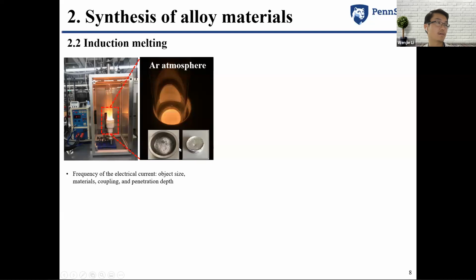we can get this molten metal homogeneous under the argon atmosphere. This is a picture of how the ingot looks. But normally, in order to achieve a homogeneous ingot, we repeat this heating and cooling a couple of times. Based on the object size, how good the conductivity of the material is, how the induction heating couples with the material, and also the penetration depth, we need to determine how high a frequency of electrical current we want to use.